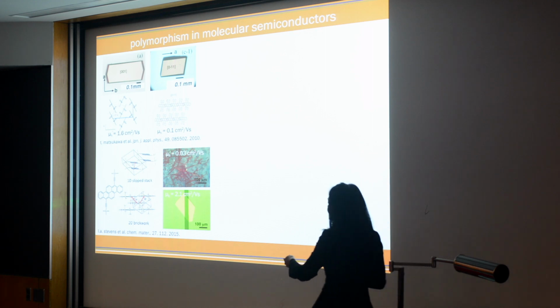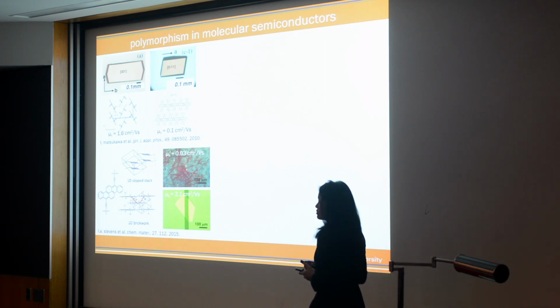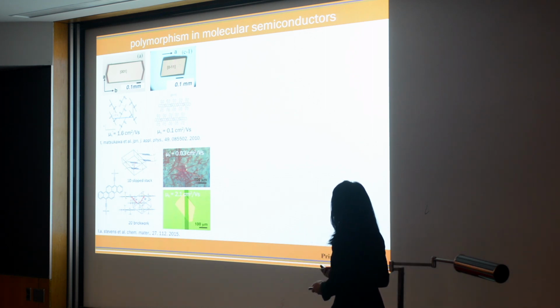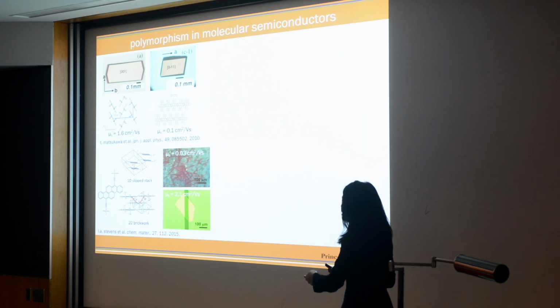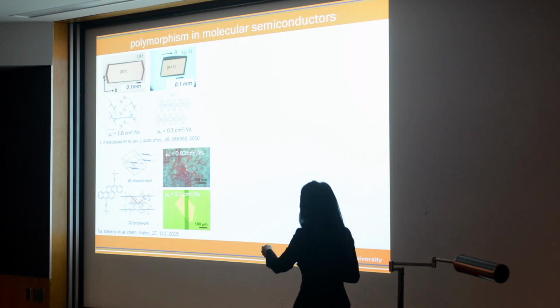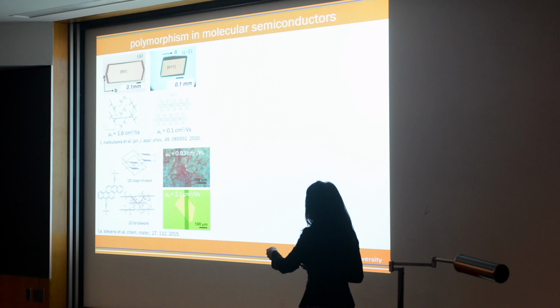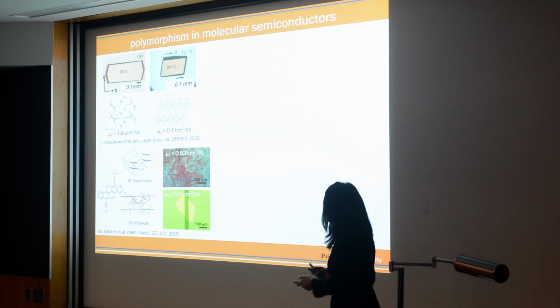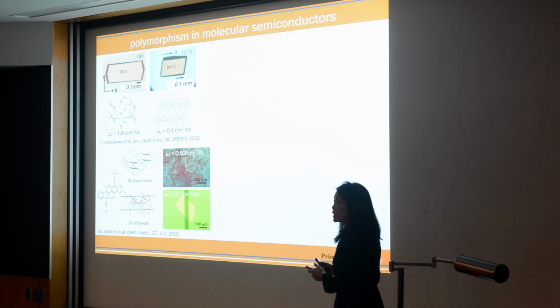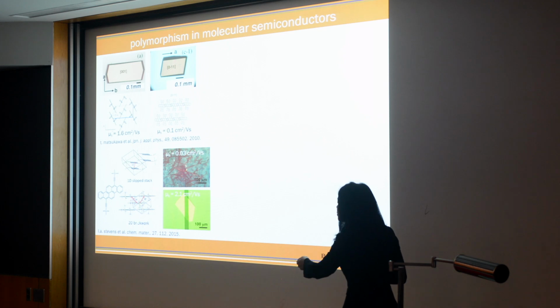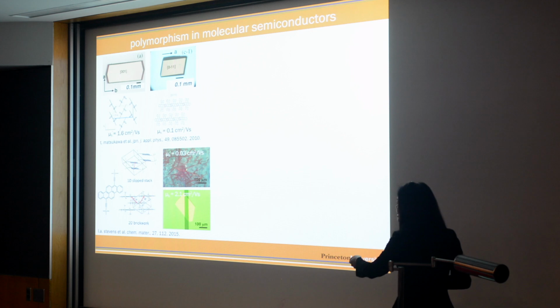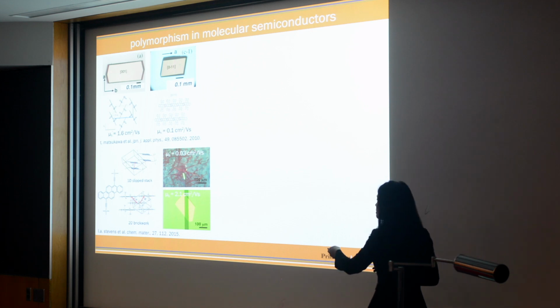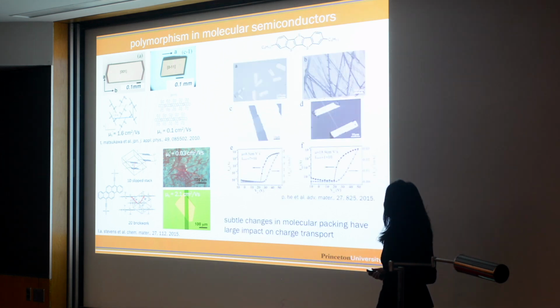This is the TMS-DBC compound that Gavin Collis's group actually grows in Australia. And Oana Dureshu's group at Wake Forest grows single crystals with this. Depending on whether you're growing it from vapor or from solution, you can again access two different polymorphs. One is a 1D slip stack polymorph, and the other one is a two-dimensional brickwork structure. These might look like cartoons, but they're actual single crystal structure data. And again, depending on which polymorph you access, you see big differences in mobility.